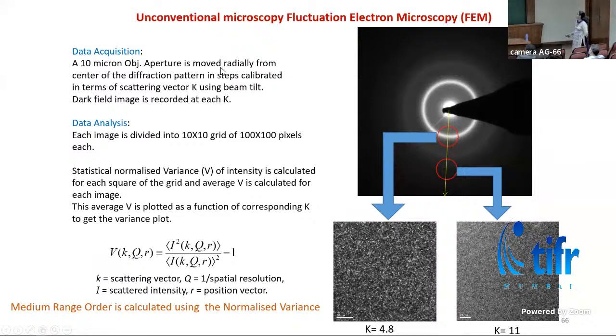This is a little unconventional microscopy. Samples which have short range order can be characterized by using neutron diffraction or EXAFS technique. Samples having long range order can be characterized by using TEM or X-ray diffraction techniques. But for samples which have medium range order, which is about 0.1 nanometer to 3 nanometers, there is no technique available to study that kind of order.